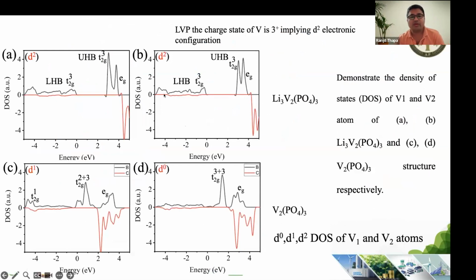Before going into that, we want to understand how the band structure or electronic structure is changing when we are bringing out all the lithium. So we have seen that when we bring out all 3 lithium from the vanadium, which we are doing only theoretically, experimentally only 1.8 lithium can come out during the de-intercalation process. But we want to see if we bring out all the lithium, then it becomes more metallic, and that is the reason why these structures are changing, from semiconductor towards metallic. From lithium vanadium phosphate to vanadium phosphate during the de-intercalation process.